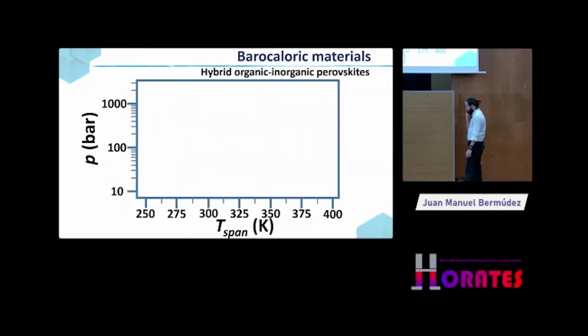So we have already seen this material, and I have already explained that. I have already shown you that this material has an entropy change similar to the metallic alloys and to inorganic barocaloric materials, but it did have one important limitation, and it was the temperature span, the range in which those materials could operate. So in this slide, I'm showing you the temperature span of different materials as a function of the pressure that you need to apply in order to make those materials able to work in this range.